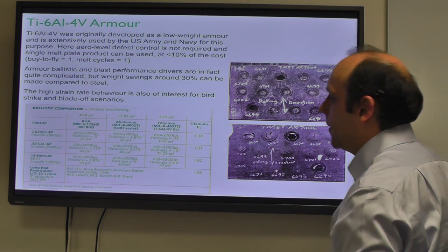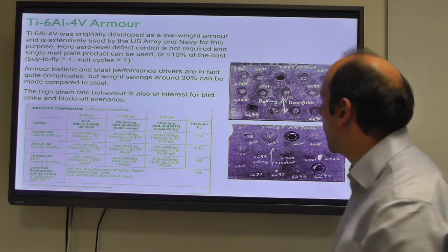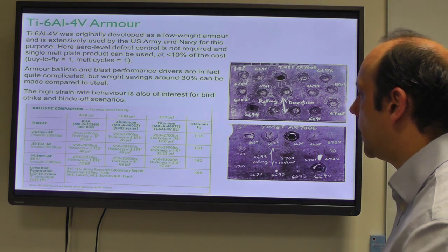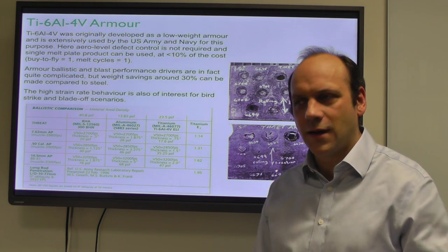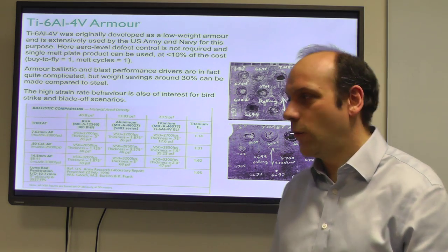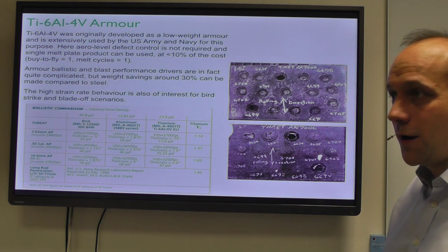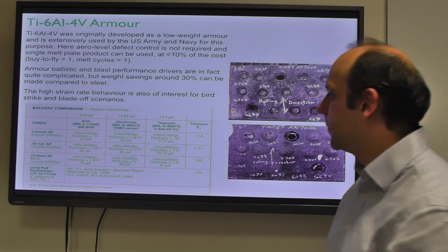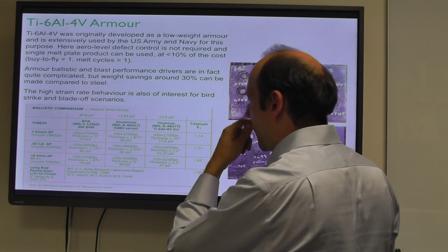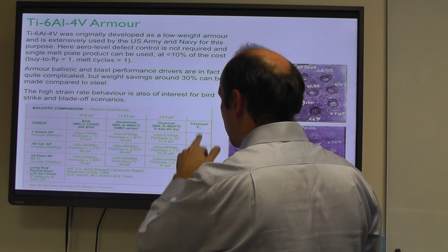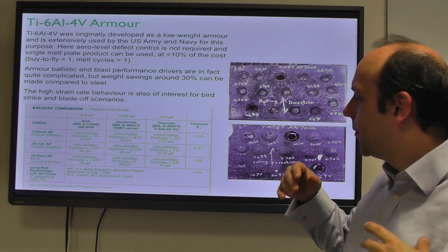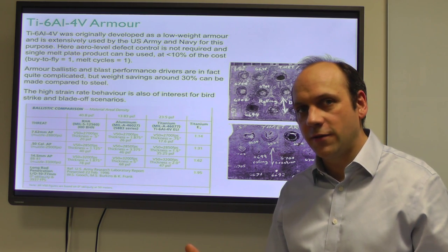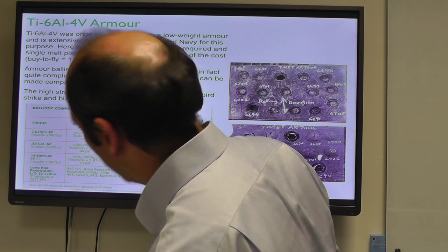You'll usually get some backside spalling because of the way the stress waves work as you go through. The way a lot of these rounds will go through the material is they will actually tunnel their way through. They will very nearly melt their way through. They take the material all the way up to its melting point. So it's actually the specific energy to melt the alloy that's the key criterion here. How much energy do you need to melt it for a given weight, rather than its high strain rate performance per se. It depends a little bit on thickness, but scanning the V50, scanning the densities, you get a performance ratio, and so you would say that against these different threats, especially against the larger diameter threats, titanium tends to perform significantly better. That's why the US Army use it for things like tanks, particularly important if you want your armoured vehicles to be air mobile, I guess. Just as a historical note there.